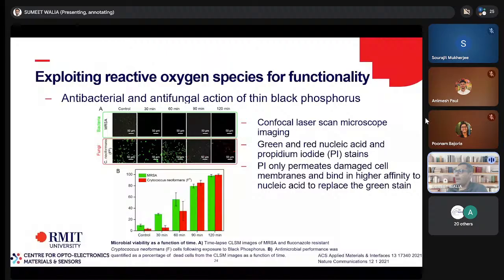So what happens is it's really good for electronics and optics in the lab, but when you're trying to scale that up, it becomes a problem because you don't want the semiconductor to decay in performance in a couple of days or 3 days and stop working. However, it turned out that when we were investigating the mechanism of that degradation, what happens is that this black phosphorus produces reactive oxygen species that degrade its surface.